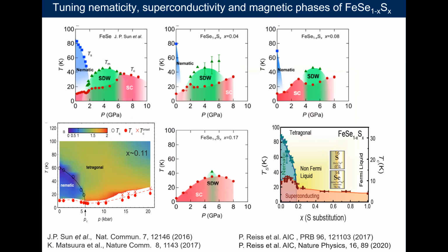And having this isoelectronic substitution, one can play with different concentrations and apply pressure to them. It's quite beautiful to see that in iron selenium, the spin density wave is more or less merging inside the nematic phase. But as we add more and more sulfur, we can push those states apart. So this gives us access to each phase individually. And I'm going to show a bit of data from the 11% sample, where we were looking to explore the nematic critical regime.